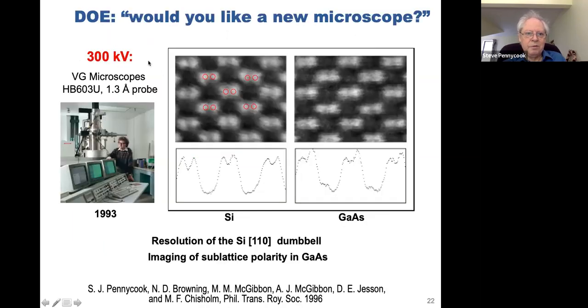Well, the Department of Energy seemed pretty happy and seemed willing to fund a higher resolution microscope, 300 kilovolt. STEMs were being built for various places, and I managed to get funding for one and persuaded VG to accept the high resolution specification, and they produced it, and then we were able to properly resolve the dumbbells in the 110 orientation of silicon. In gallium arsenide, we could distinguish arsenic from gallium based on the Z contrast. So this was very nice.